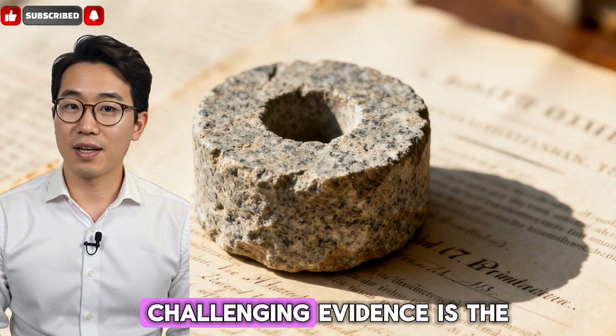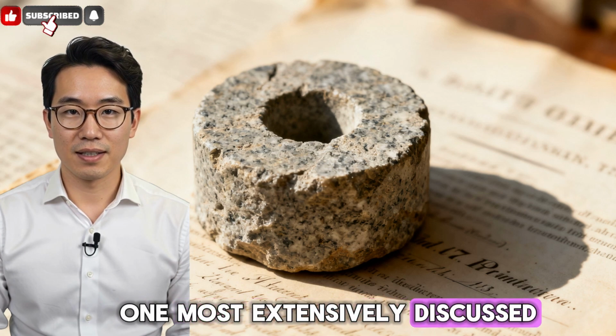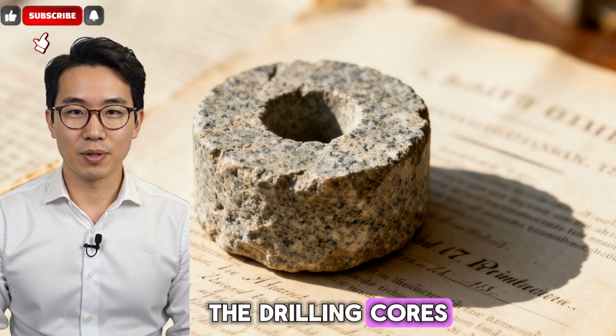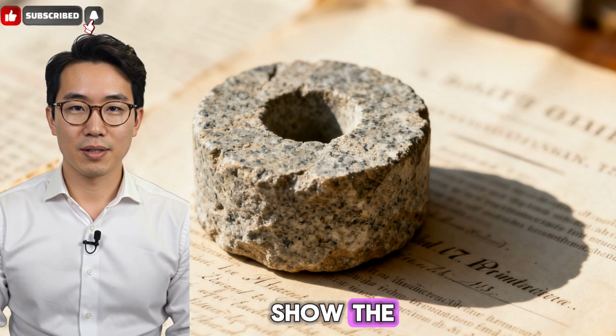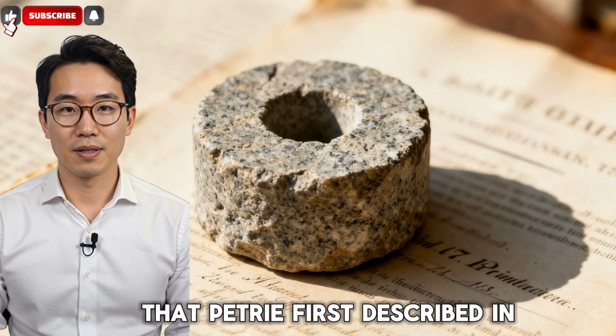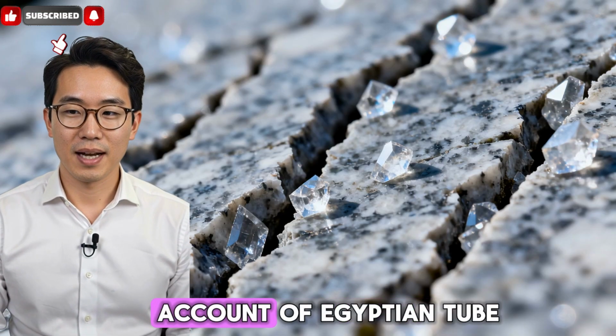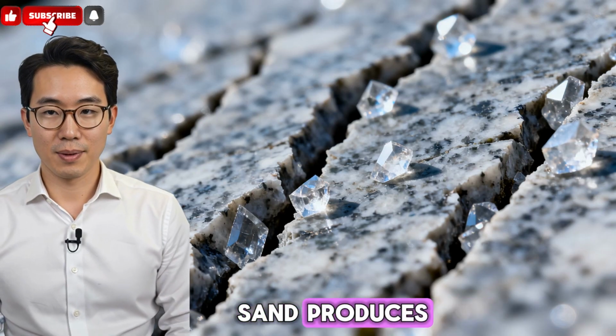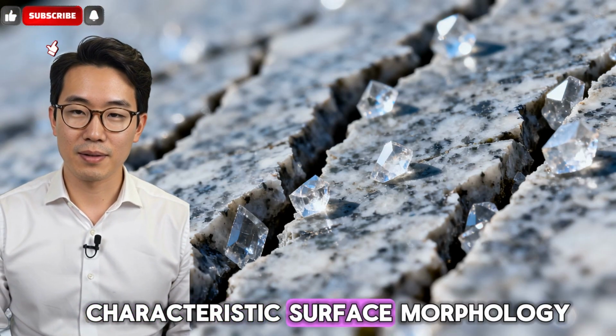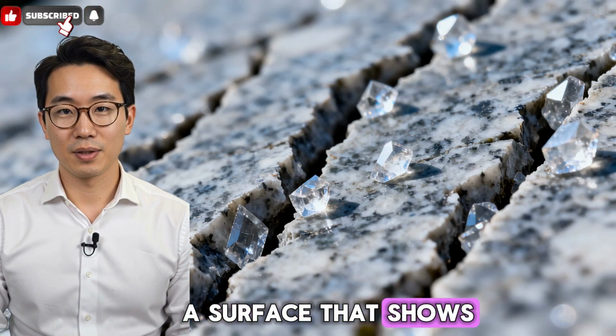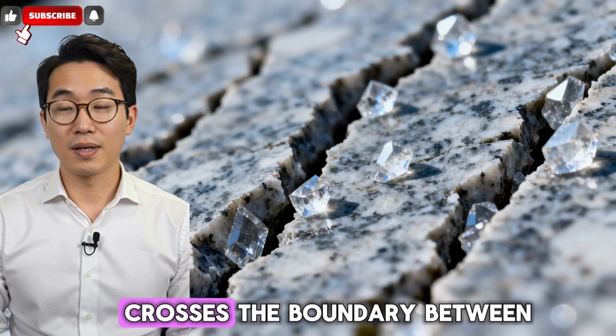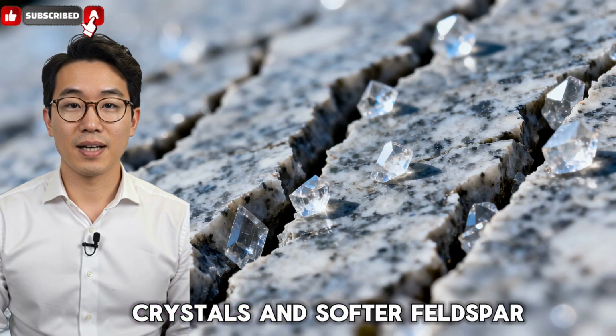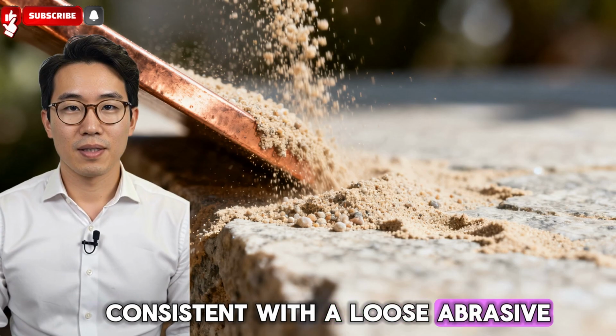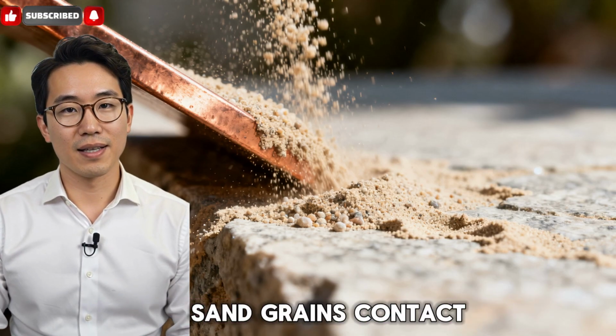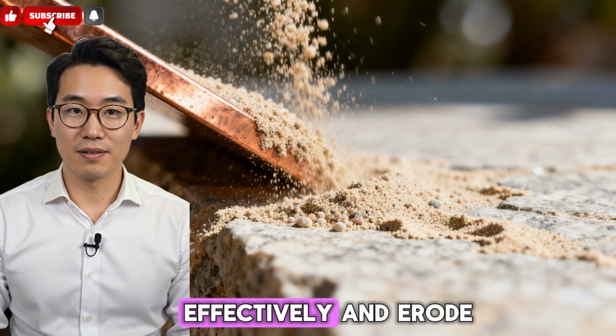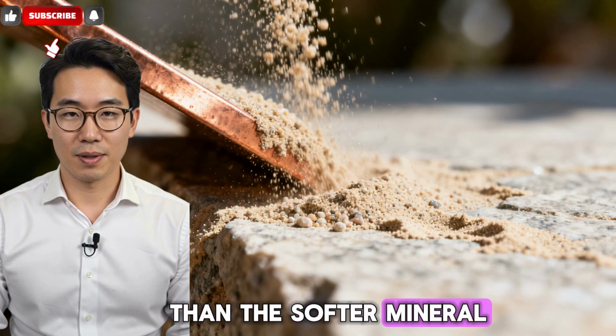The second category of challenging evidence is the one most extensively discussed in the technical literature, the drilling cores, specifically the examples that show the anomalous surface characteristics that Petrie first described in 1883. The mainstream account of Egyptian tube drilling with copper and sand produces drilling cores with a characteristic surface morphology, a surface that shows a regular depth variation as the drill crosses the boundary between harder quartz crystals and softer feldspar, consistent with a loose abrasive process in which individual sand grains contact the harder mineral less effectively and erode it more slowly than the softer mineral surrounding it.